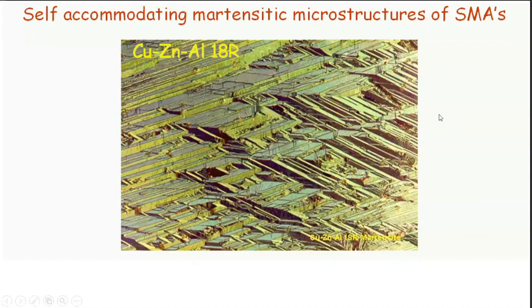And the way to see it is, if you see these four of them, you see, I have to fight with this mouse also. So you see 1, 2, 3, 4. It's something like a wedge. So this is called the diamond morphology, and this is like several chevrons piled into each other. And this kind of diamond morphology has one of the particular groups of four variants which are together. So six such groups come together and give you the 24 orientation variants.